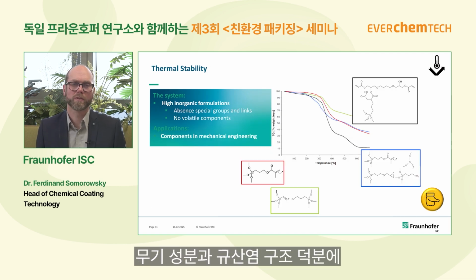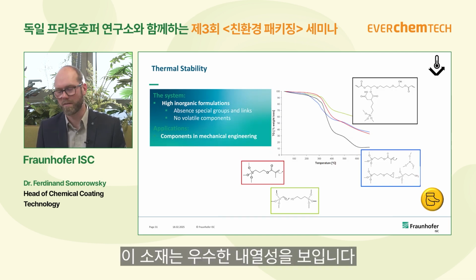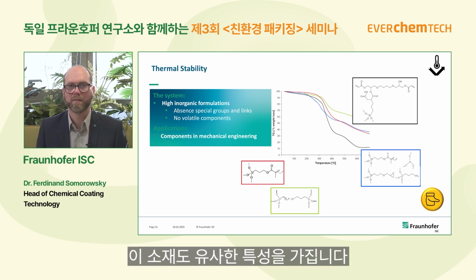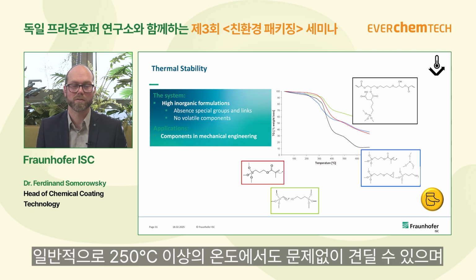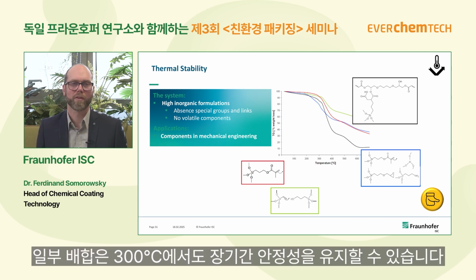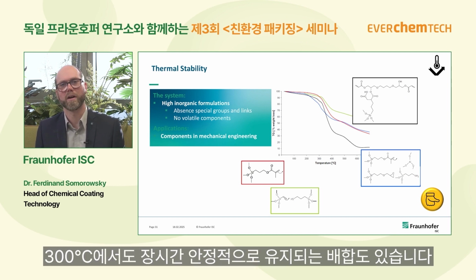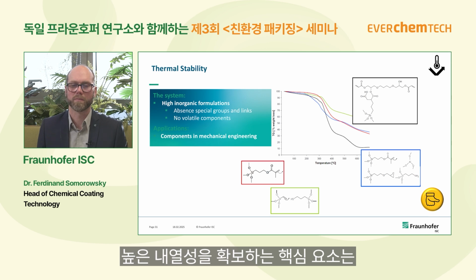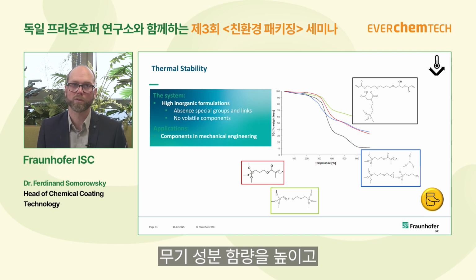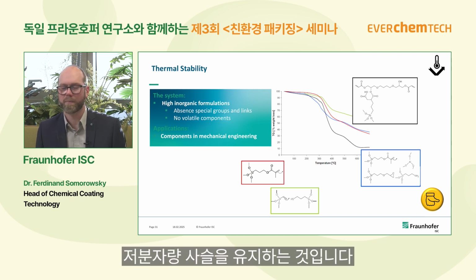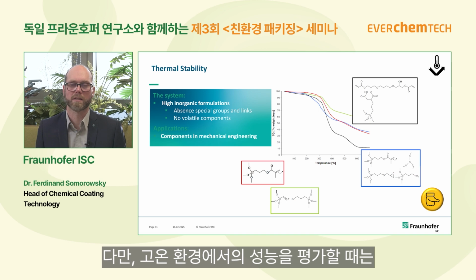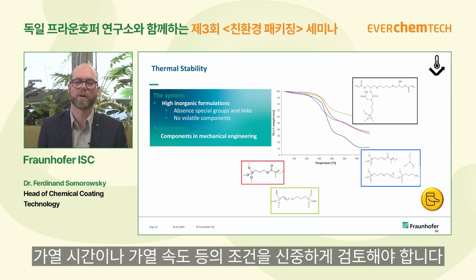Temperature stability: due to this inorganic content and silicate structure, everybody knows very well, glasses are very inert to high temperatures. The Ormocer can also have a high stability here. More than 250 degrees is normally not a problem. There are even formulations that are stable up to 300 degrees, also for a longer time. And the key here is to have a high inorganic content, to have low molecule chains, and so up to a certain temperature the Ormocer can also be an alternative here, but you have to double check how long, what is the heating rate, things like that.